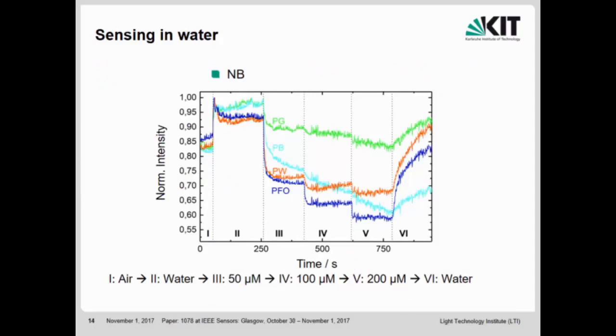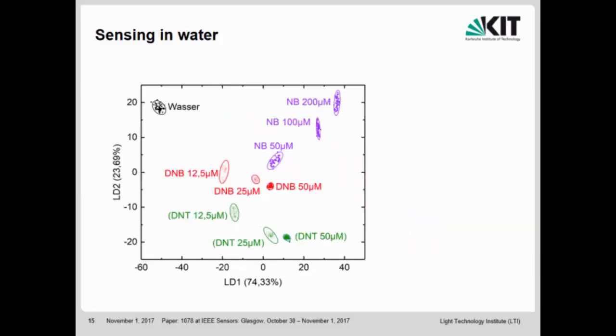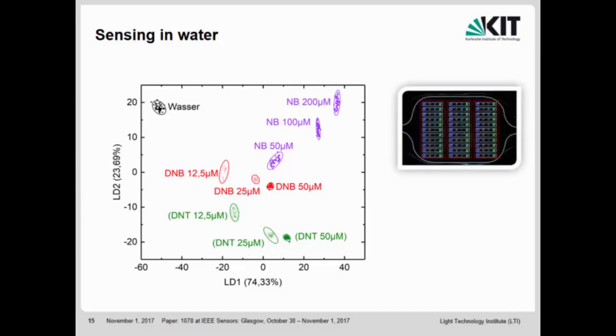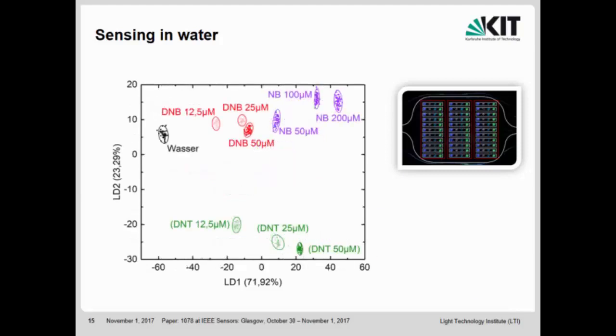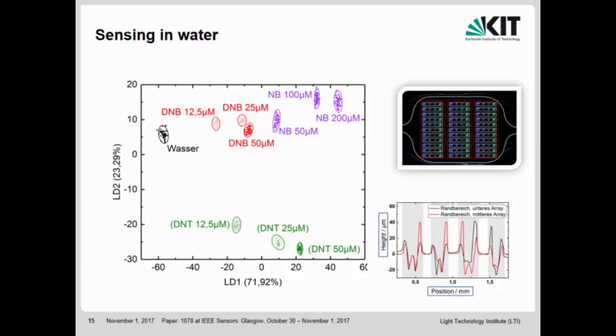And then we went into the microfluidics and measured the whole thing, and one of these measuring examples you see here. The first thing was we measured in air, we filled it with a liquid, continuously increased the amount of quencher within the water, and then applied a linear discriminant analysis to differentiate. And here we have the following problem, that not all of these single arrays worked perfectly, because some of them, you may remember this image, have a really high sidewall, and some of them are blocked by air bubbles, because when you go from one solution to another with a different concentration of the quencher, there might be air bubbles and they are blocked.